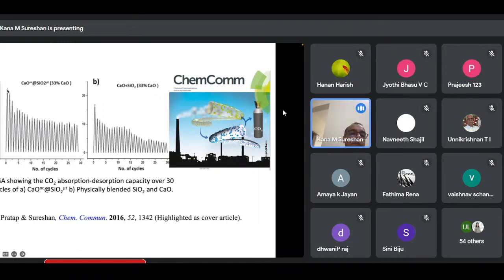Initially, it has taken 23% of carbon dioxide. Then it reduced slightly. And after 30 cycles, each cycle being carbonation and decarbonation, this is the weight percentage. After 30 cycles also, we have about 12 to 13% by weight. That means 100 gram of this material can take about 12 to 13 gram of carbon dioxide even after 30 cycles, which is good. If you take the same composition of calcium oxide and silica, physically mixing calcium oxide and silica, of course, this is very low.